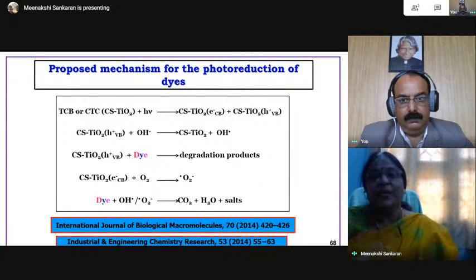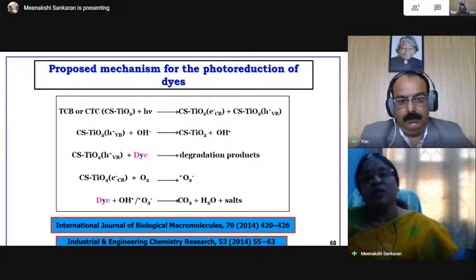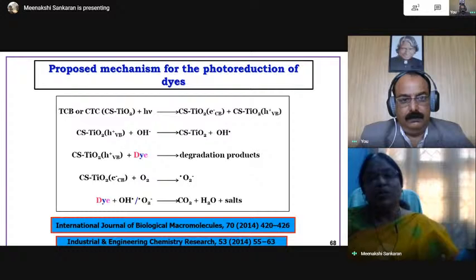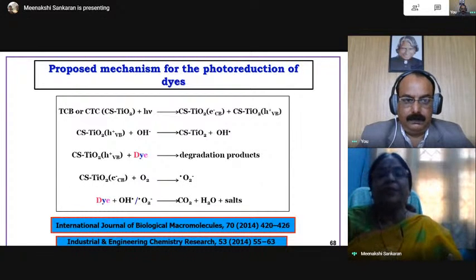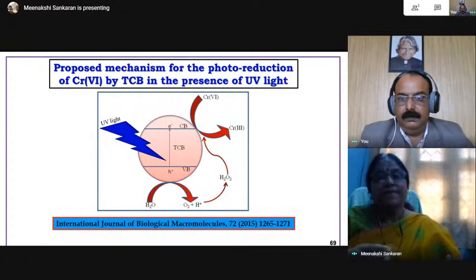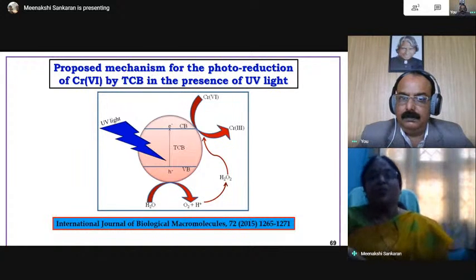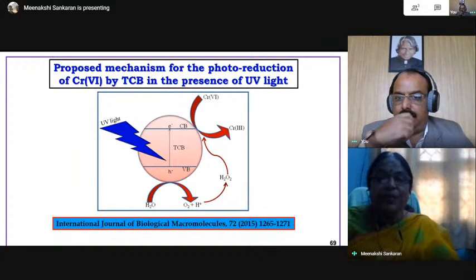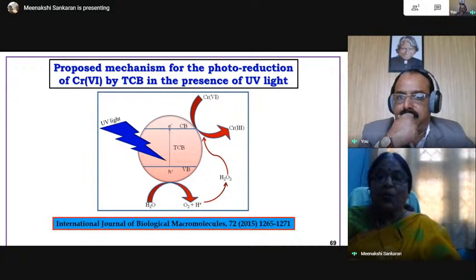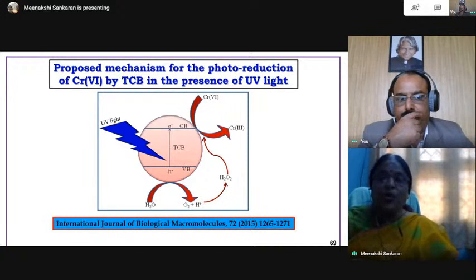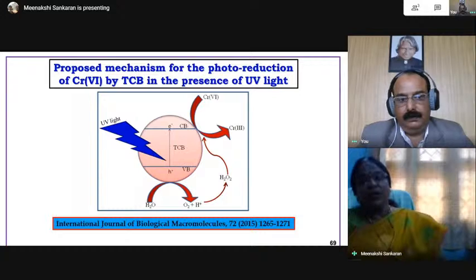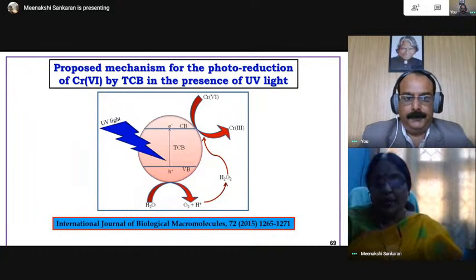Hole we need separately and the electron we need separately. They will react with water and be converted into hydroxyl radicals and superoxide radicals. They are capable of removing dyes and also heavy metal, that is chromium. And this is the same: chromium 6 has been reduced to chromium 3, and the hole is converted to hydroxyl radical, which degrades our dye molecules.